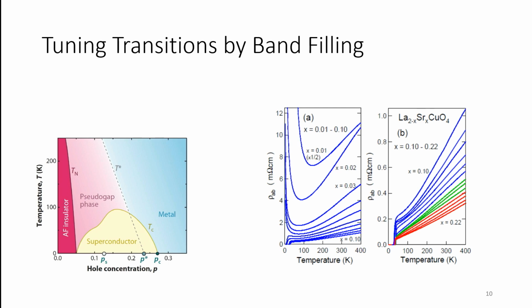And as you add more and more strontium, you're effectively adding holes into the system. You're doping the system with holes, and the resistance goes down. The system becomes metallic and superconducting. And this is what is shown in this phase diagram here.